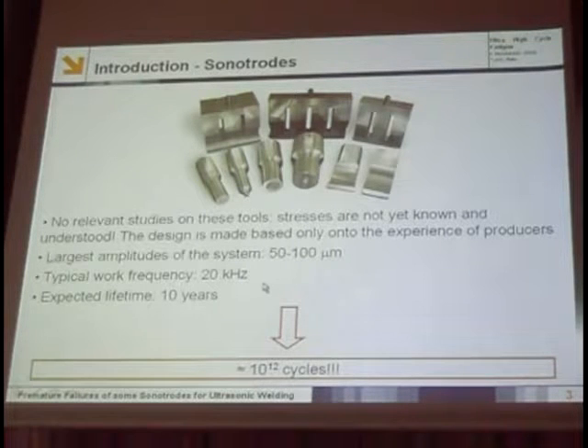The typical work frequency is 20 kilohertz. Usually the expected life, and I say expected because I know from our customer, who is a producer of sonotrodes, is that they work for 10 years. So imagine 200 working days in a year and 8 hours a day. In 10 years we have sonotrodes working for 10 to the 12 cycles, a very huge amount of fatigue cycles seen by this kind of tools.